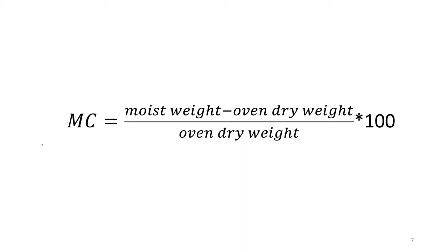After oven drying a piece of lumber, yes, there's probably a tiny 0.01% of moisture left over. We just define that as zero moisture content because for all intents and purposes, it is close enough. However, this is usually a destructive process. You first need to cut the lumber sample small enough to fit into a high temperature oven. And oven drying completely often causes cracking and other destructive effects.